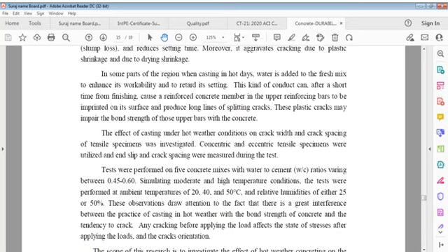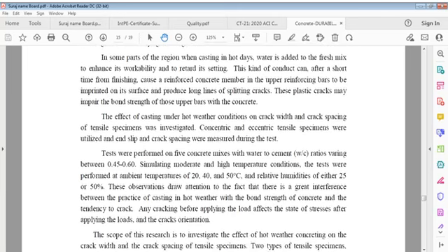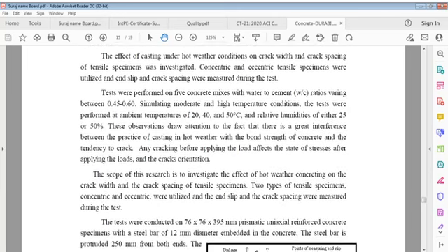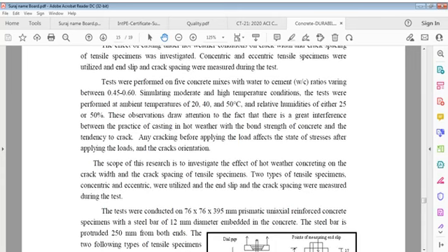The effect of casting under hot weather conditions on crack width and crack spacing of tensile specimens was investigated. Concentric and eccentric tensile specimens were utilized, and end slip and crack spacing were measured during tests. Tests were performed on 5 concrete mixes with water cement ratio varying between 0.45 to 0.6, simulating moderate and high temperature conditions.